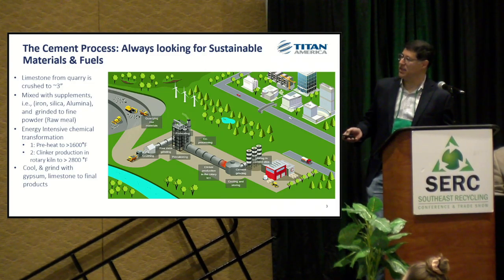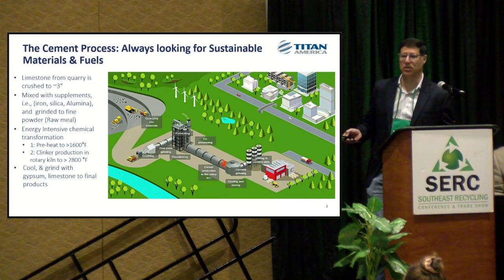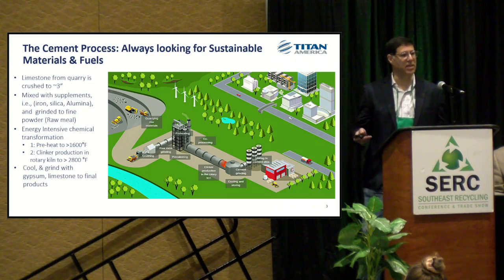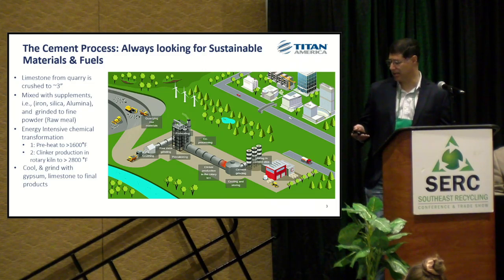After the material comes out at the end of this little tube here, it is cooled very rapidly, in a matter of seconds, to about 300 degrees. Then it's transported, crushed and ground with gypsum and limestone to make the final product. That is what you see on the bags, typically at Home Depot and the big box stores.